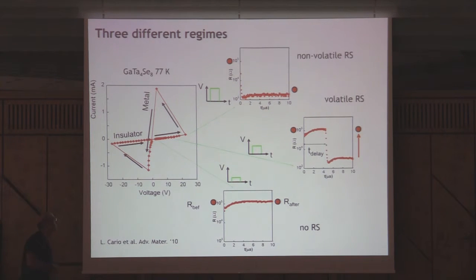On the other hand, when you do the systematic study, you find out that when the voltage is not so high and not so low, there is a regime in the middle where you have this resistive transition, but it is volatile. That is, when your pulse is terminated, the system comes back to the original value. And this effect here is perfectly reproducible. You can do this 10,000 times, and you'll get point-by-point reproduction of this behavior.